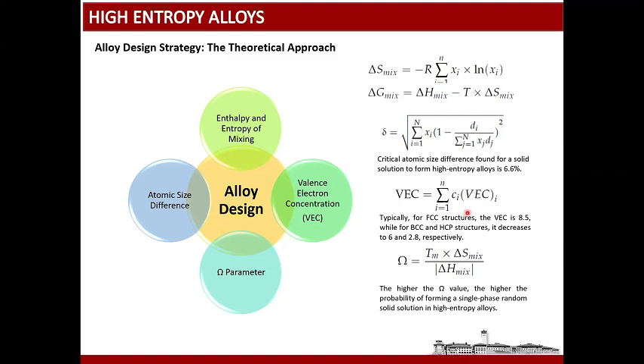Valence electron concentration determines the structure. We know the metals in the periodic table have either FCC structure, BCC structure, or hexagonal close-packed structure. For FCC structure, the valence electron concentration is around 8.5, but for BCC or HCP structure, it decreases to 6 and 2.8. So by controlling the valence electron concentration, we can control the structure of the final product. The omega parameter is also another important parameter to design high entropy alloys. The higher the omega value, the higher the probability of forming a single phase random solid solution in high entropy alloys. So these are again different design strategies to obtain the desired high entropy alloy.